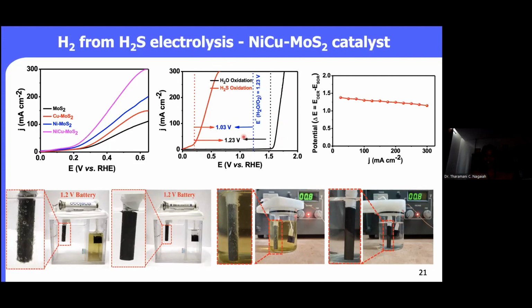Now let's compare the potential, that means how much potential we are saving here. If we compare with respect to the thermodynamic potential, we are saving almost 1.03 volts of energy compared to the electrochemical water splitting. When we compare this with respect to the measured potential with the proposed catalyst, we are saving almost 1.23 volts. And when we compare the potential at various current densities in both the processes, there is a small decay in the current. However, it is quite stable.